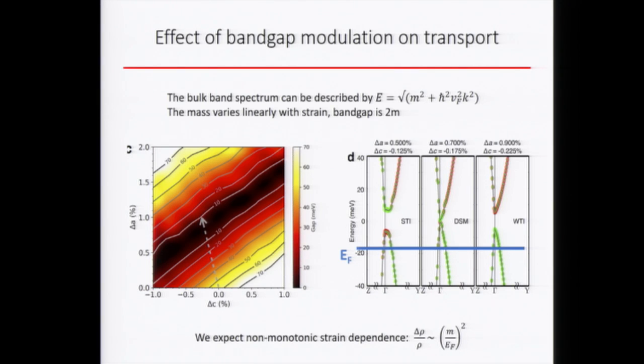So what you are seeing is the transport property of some bulk, massive or massless Dirac fermion, and the mass is modulating as a function of strain. So what you will expect is that the resistance will go down when you are going to a massless Dirac state and then going back up again. In addition, they should depend on the mass in a very specific way. Your mass could change sign, from positive to negative, across this topological phase transition, but your resistance shouldn't depend on the sign of the mass. Therefore, the lowest expansion is the quadratic expansion. So if you can tune the mass linearly across the topological phase transition, you should expect a quadratic dependence of the resistance as a function of strain.